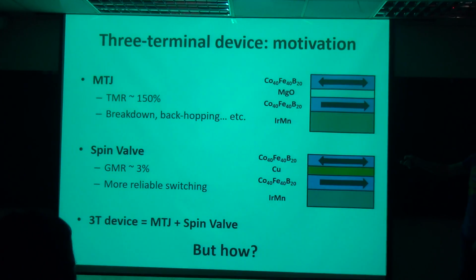For tunnel junctions, like I just mentioned, you typically use MgO as your tunnel barrier, and you use cobalt iron boron, sort of amorphous magnetic alloys, as your ferromagnetic electrodes. And for the spin valve, we use cobalt iron boron, copper, and cobalt iron boron. The reason why we use cobalt iron boron is because we want this to be compatible with the tunnel junction part. And copper is a typical metallic spacer layer, so that's the reason why we choose copper. And so we want to combine these two.